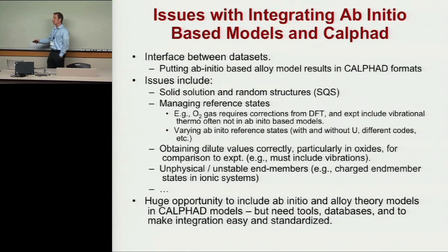There's stuff to think about there, tools to develop, things to automate, and to understand. There's a lot of subtle issues of reference states. If you're going to work with the CALPHAD community, you have to have the same reference states they do. They reference to oxygen gas, right? We don't usually reference to oxygen gas, and it's not a nice thing to calculate because it comes out wrong. So you have to fix that, and you have to make sure that you have those reference states consistent with what's done in that community. Other issues about dilute heats of mixing and values, including vibrational effects, including size effects like BJ talked about.